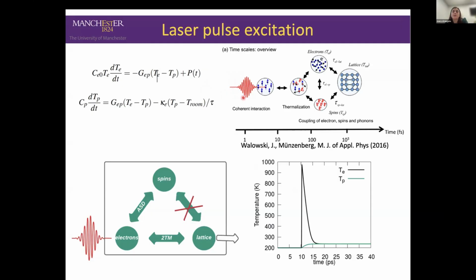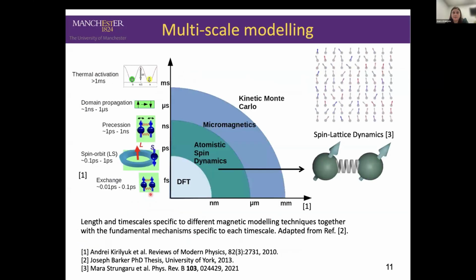In this framework, the laser connects to the free electrons in our magnetic systems. There's an increase in the electronic temperature, which further thermalizes with the lattice and the spins. What we do in atomistic spin dynamics is basically model what's called the two-temperature model, as shown in this coupled equation here, that gives the profile of the evolution of the electronic and phonon temperature as a function of time. And then we couple our spins to the electronic bath via atomistic spin dynamics, and we are able to look into the evolution of magnetic systems under ultrafast excitation.